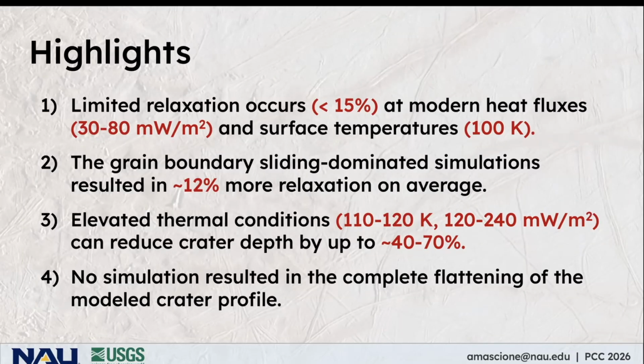It's important to note, however, that none of our simulations resulted in the near complete flattening of the impact crater. So this tells us that regardless of any potential elevated heat pulses, other processes like shallow formation, sublimation erosion, and isostatic adjustment can collectively contribute to a significant fraction of post-impact shallowing on Europa.